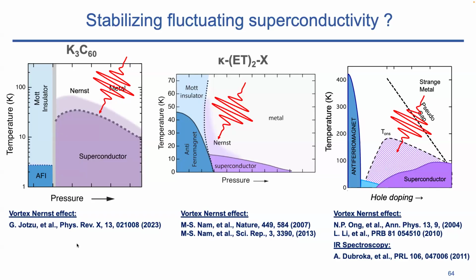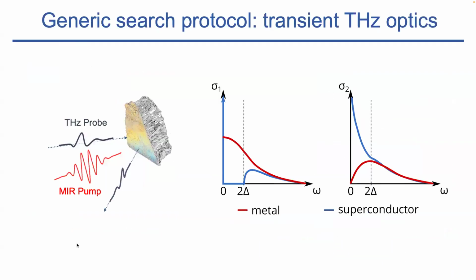physics in this problem. All right, so you take these materials, and what you want to know, so this is now your material, which is your candidate material to show photoinduced superconductivity. You use a mid-infrared pump pulse to drive a particular phonon, which you choose based on a combination of calculations, but also maybe intuitive argumentation. And then you use a terahertz probe pulse.